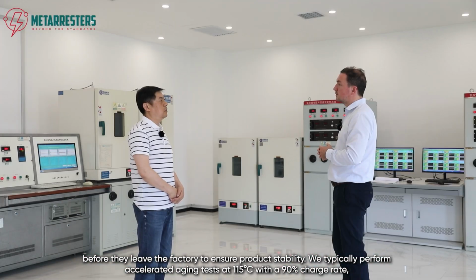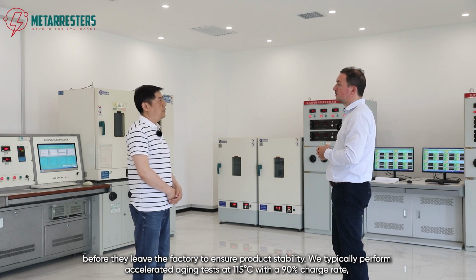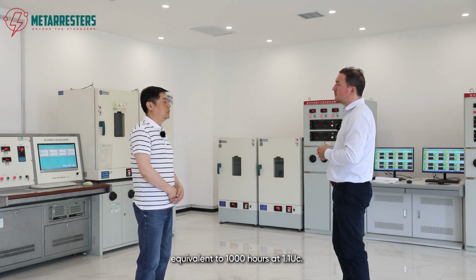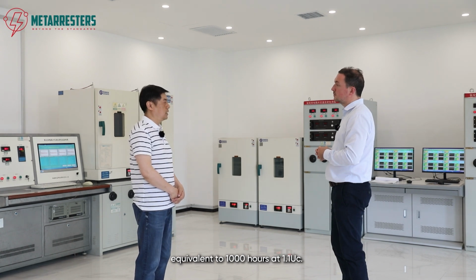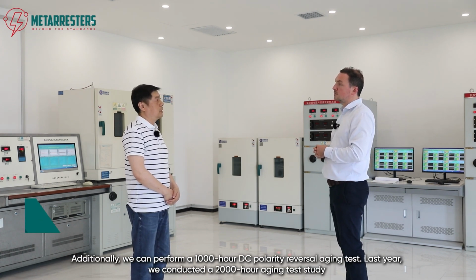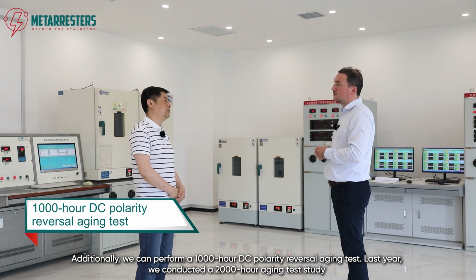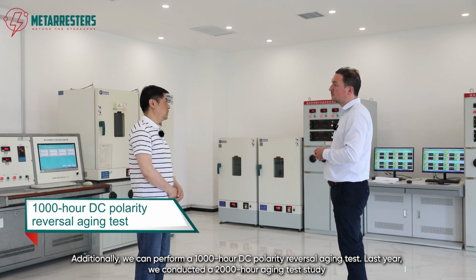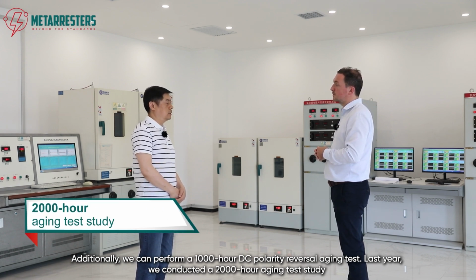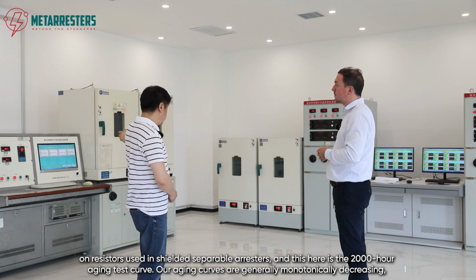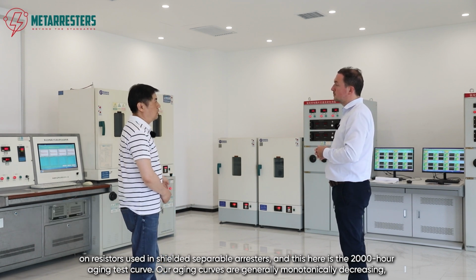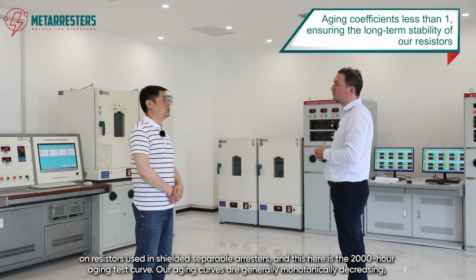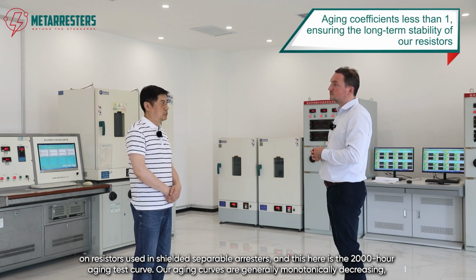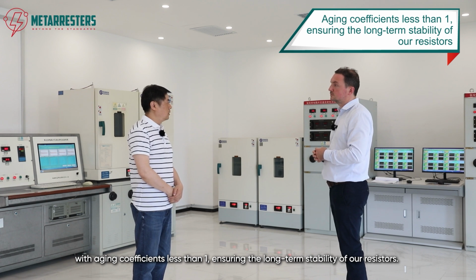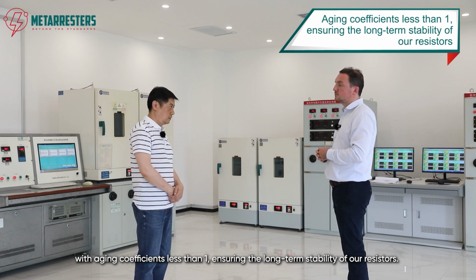We typically perform accelerated aging tests at 115 degrees Celsius with a 90% charge rate, equivalent to 1,000 hours at 1.1 UC. Additionally, we can perform a 1,000 hour DC polarity reversal aging test. Last year, we conducted a 2,000 hour aging test study on resistors used in shielded separable arrestors. And this here is the 2,000 hour aging test curve. Our aging curves are generally monotonically decreasing with aging coefficients less than 1, ensuring the long-term stability of our resistors.